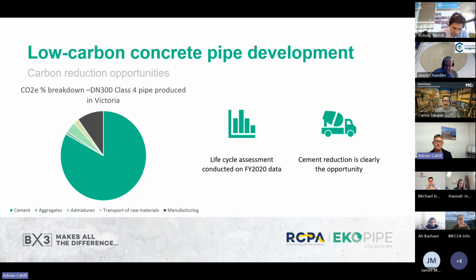the vast majority is the cement content. So this was based on an example product in Victoria, and you see that more than 80% of the CO2 embodied carbon comes directly from the cement content. So that's obviously the opportunity.